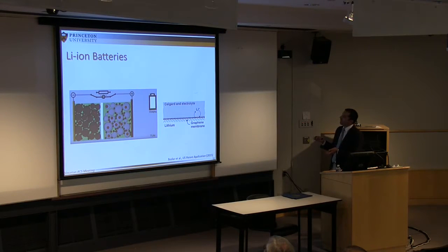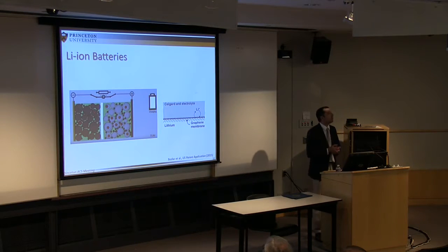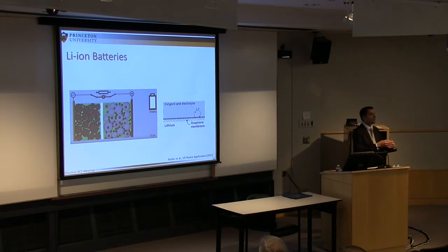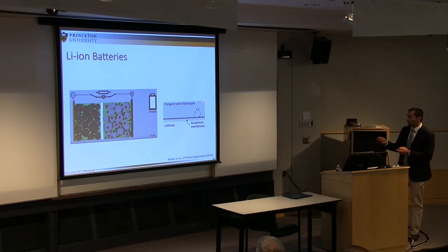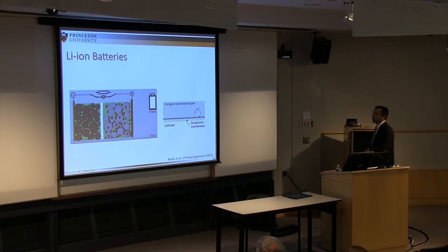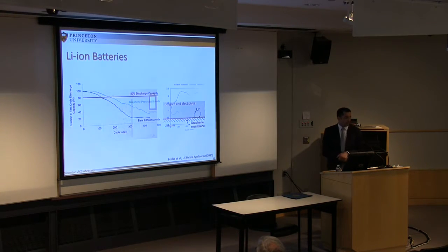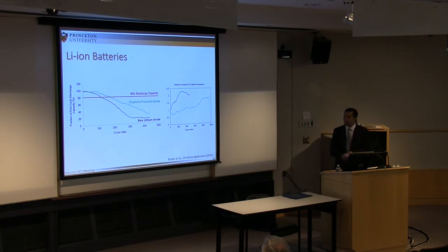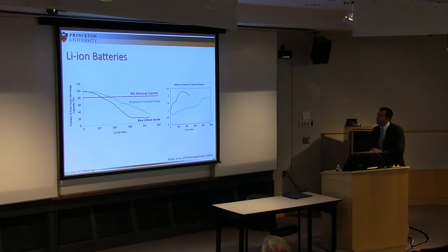So the idea we had was to have a graphene coating in between the separator and the lithium metal. And why is graphene interesting here? Because it can allow lithium ions to shuttle back and forth while preventing the electrolyte from being in contact with the lithium metal. All of this was with the objective of improving the cycle life of the battery.